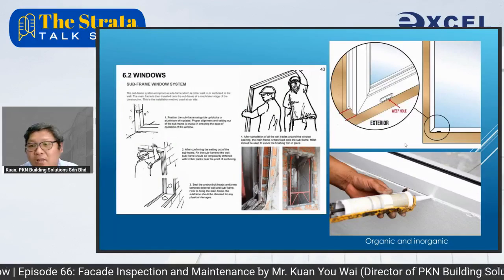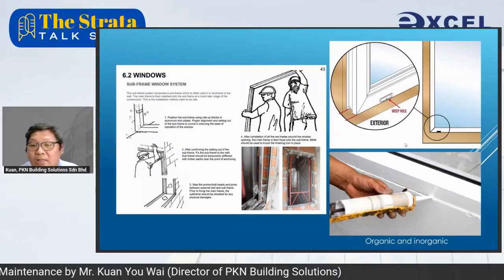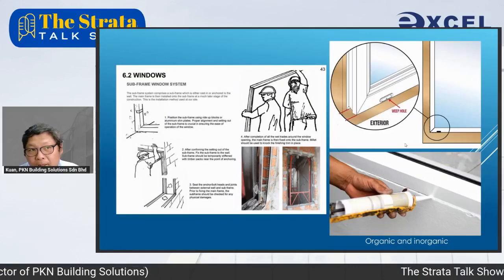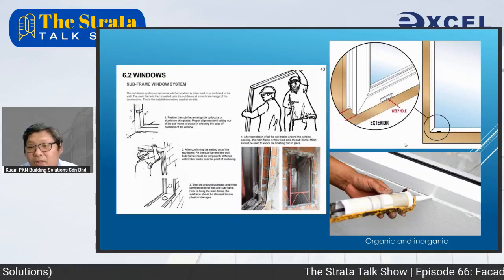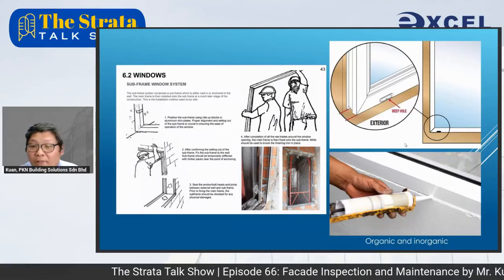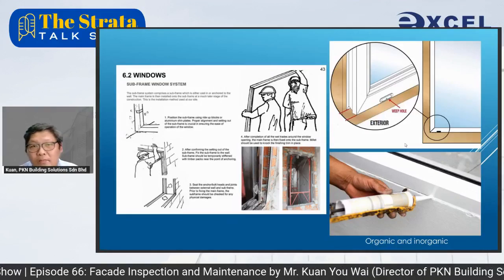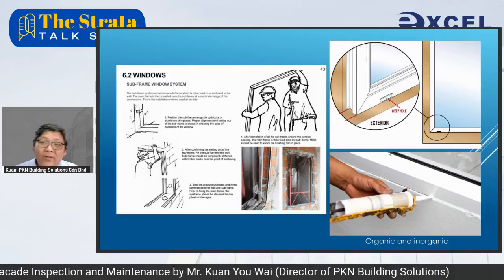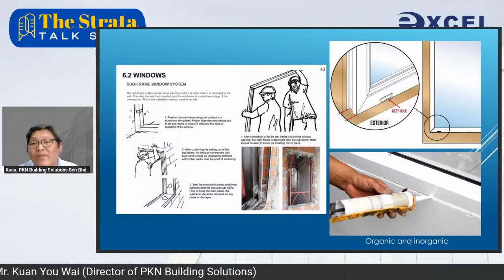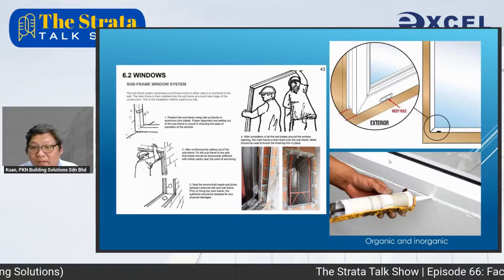And of course, the biggest problem with a window is the sealant. Sealant is not durable. It needs maintenance over the years. And sealant comes as organic and inorganic sealant. Organic sealant is made from a petrochemical product, and inorganic sealant is made from silicate. Silicate means it actually comes from sand, and organic literally comes from petroleum. Under the hot sun in Malaysia, the tendency to fail is faster for the petrochemical one, because petrochemical is not ultraviolet stable, naturally.